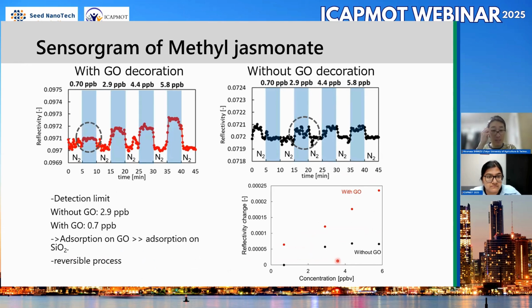So this figure shows the sensor graph for methyl jasmonate. The left figure shows the sensor graph with graphene oxide decoration, and the right figure shows the sensor graph without graphene oxide decoration. You can see that with increasing concentration, the reflectivity change becomes larger. And the detection limit for methyl jasmonate is 0.7 ppb with graphene oxide decoration and 2.9 ppb without graphene oxide decoration.